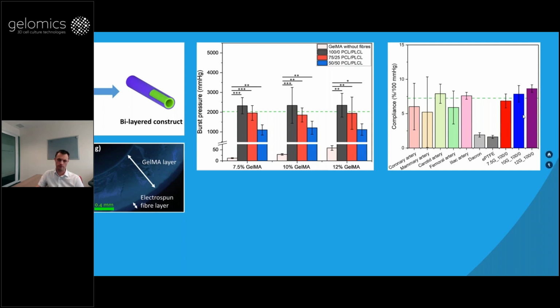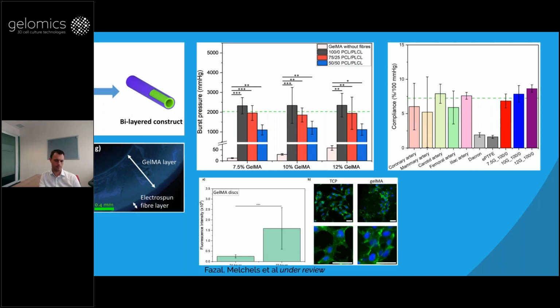On the right, those are three formulations we work with. On the left is a lot of natural arteries, and the Dacron and PTFE, those are things used in the clinic for blood vessel grafts, but these are much stiffer, so their compliance is a lot lower. So we managed to get much closer to native blood vessel properties, and could again seed endothelial cells on Gelma to endothelialize.